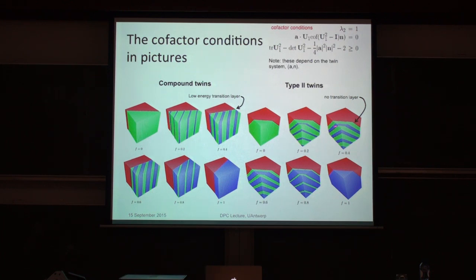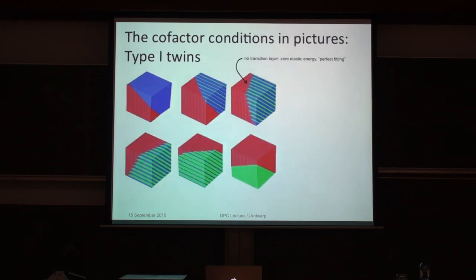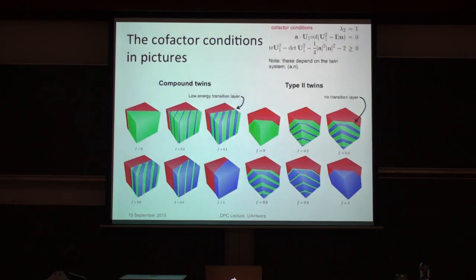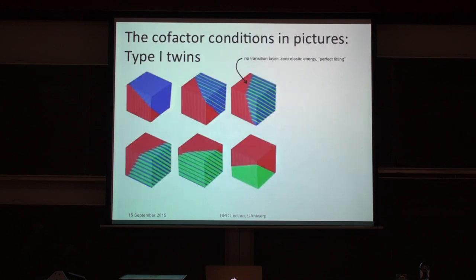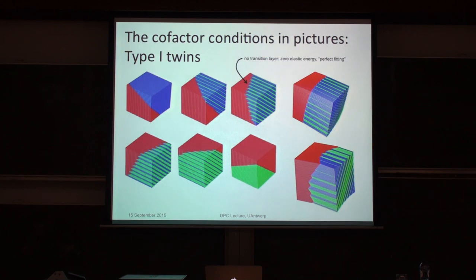There's some very interesting cases where these are parallel to the austenite martensite interface. This is for type 1 twins. Actually, in this case, you can completely remove the transition layer. So this is a case where everything is fitting together, and there's no transition layer. There's zero elastic energy in all those pictures. And then when you see that, you realize you can actually make curved interfaces. So if you satisfy these particular conditions on lattice parameters, you have tremendous flexibility in the way the two phases can fit together.